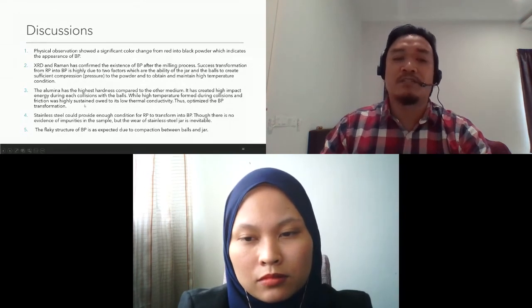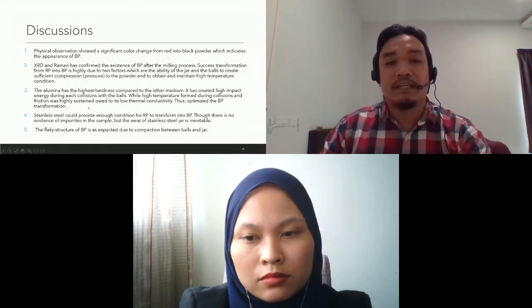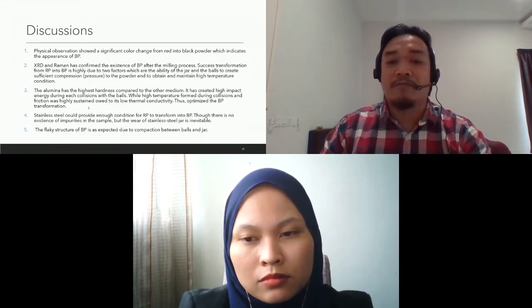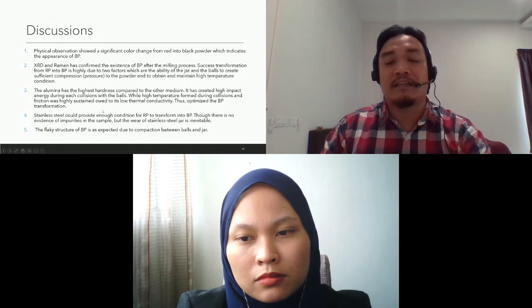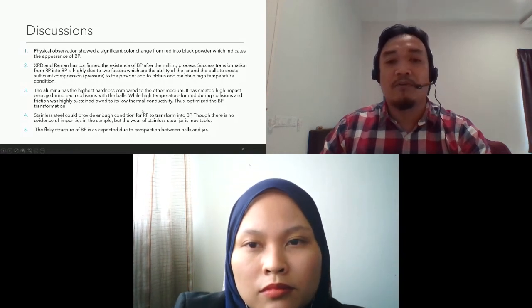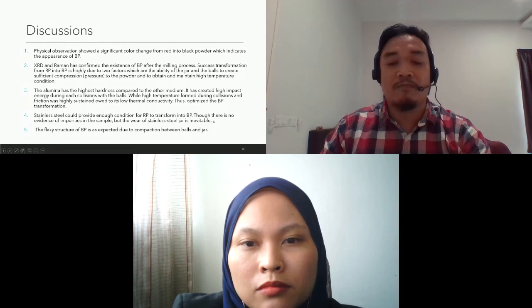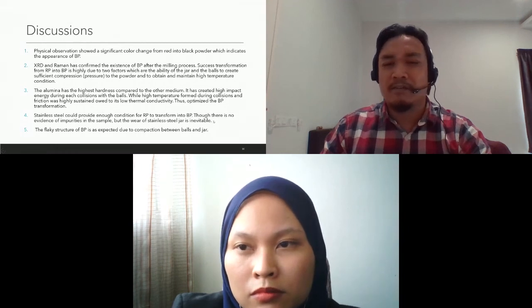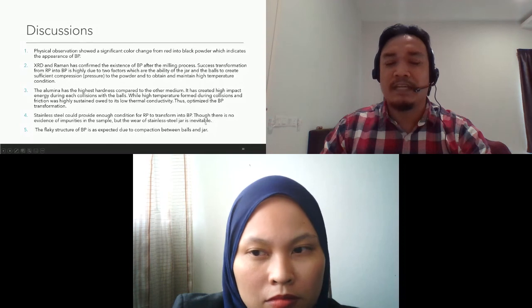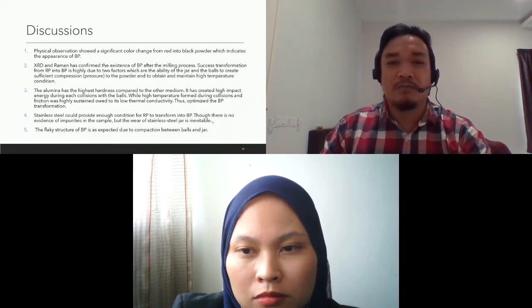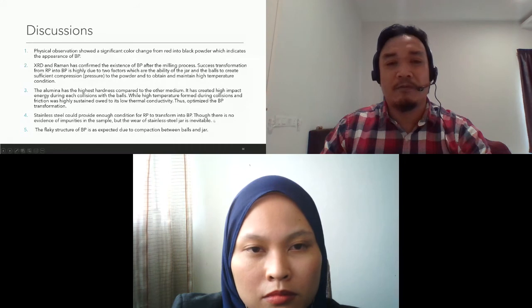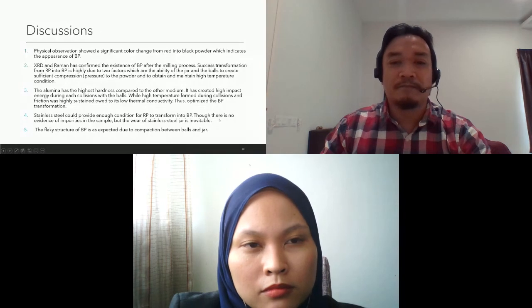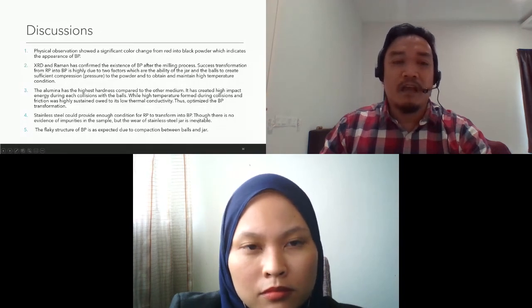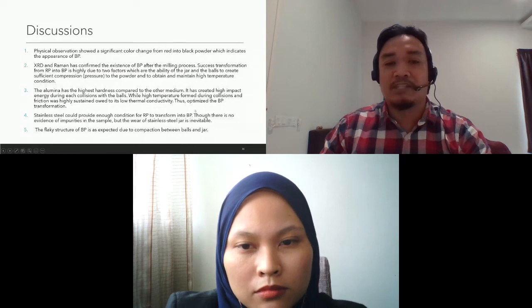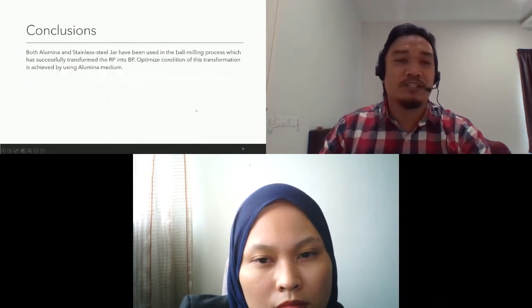Though there is no evidence of impurities in the sample as shown in XRD, the wear of the stainless steel jar is inevitable for a very long period of milling. If we exceed 2 hours, or go for 3 or 4 hours, maybe there will be some evidence of impurities because of the wear of the stainless steel jar. And the flaky structure of BP is as expected due to compaction between balls and jar.